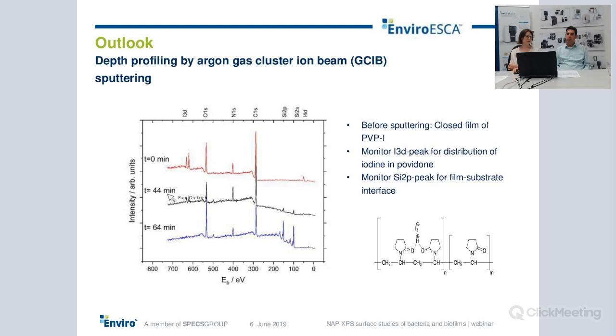After 44 minutes, you see obviously that the iodine 3D peak is lower in intensity, but the signal from oxygen, nitrogen, and carbon is approximately constant. And you start to see a signal from silicon, which is the substrate.